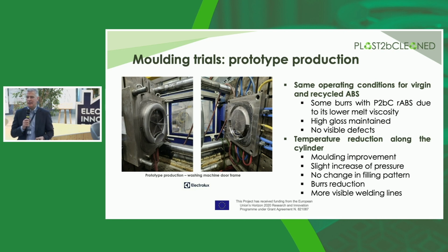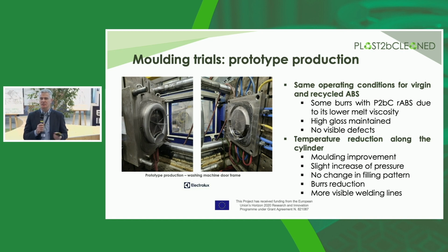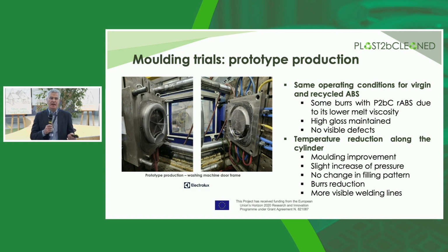Okay, so in the end, we were able to use the material after recovery from scraps, and the final step, of course, is to really produce some parts, and that's exactly what we did. We just used the prototype mold for a porthole frame for a washing machine, and what was really important is that first of all we really used the same operating conditions typical for a virgin ABS.